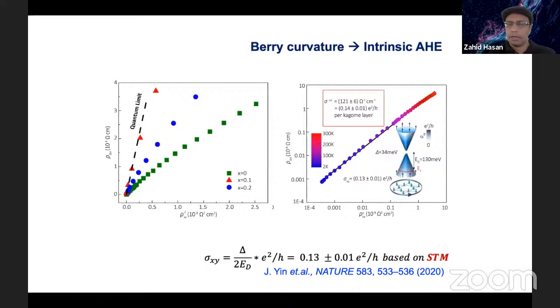I found it quite surprising that when we compare with the transport data, we fit the anomalous Hall signal in this compound, and the transport fit gives a gap of 34 millivolts, and the Fermi level shift is 130 millivolts. So this is quite remarkable. I don't know of any spectroscopy agreeing so much with transport. It's very remarkable, probably some material coincidence. But on the other hand, the material is so clean, it's not too surprising either. So we have to worry about modeling disorder less than in other compounds.